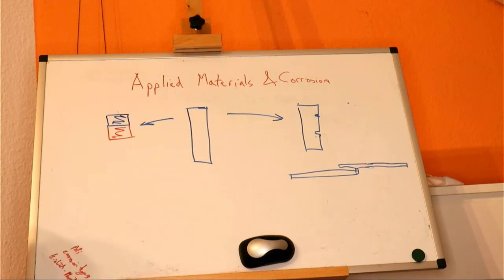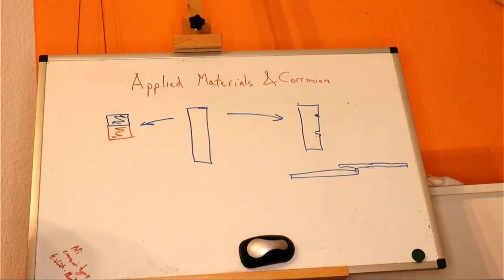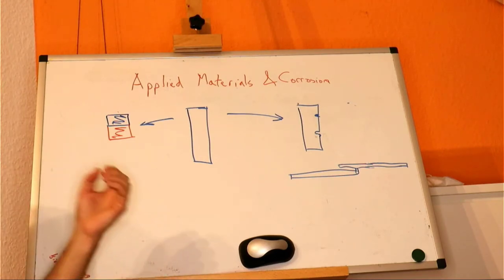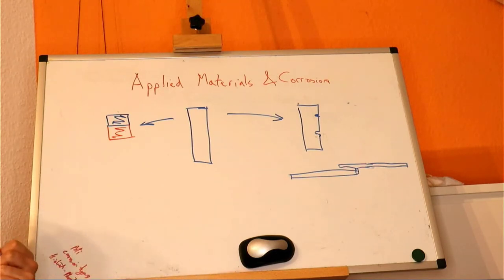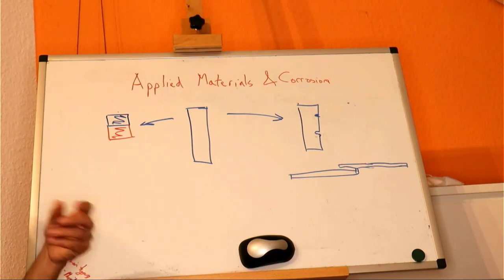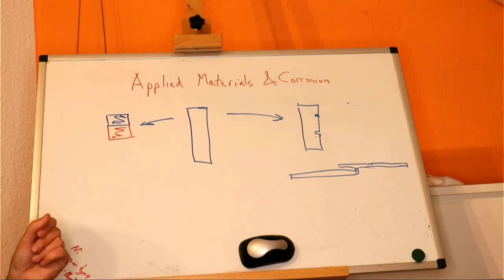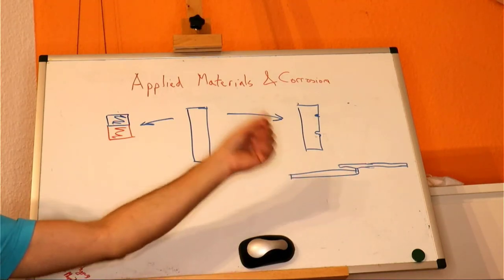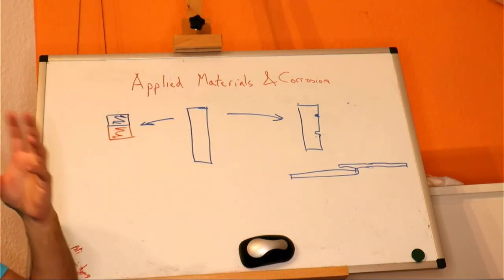That's fine in the dry, but in the wet some water gets trapped in here, and we have the problem that we had last time in our electropolishing. We were using it last time because the materials, in that case it was metal ions, can't diffuse out very quickly from a small pinch. Then their concentration goes up, and so the rate of corrosion goes up inside the pinch. Here we've got oxygen getting used up inside the hole, and that will cause one of two things.